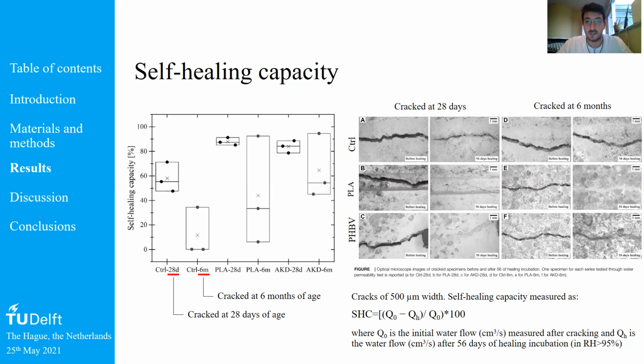So we can see how positive is the influence of our healing agents included in the matrix for cracks that are relatively big. That is also further confirmed by the pictures on the right, where you can see the first row related to the control series. Cracked at 28 days there is quite a bit of precipitates that cannot, however, fill up the crack completely, while for those cracked at 6 months the crack is more or less the same, so there is not enough precipitation to seal the crack for the control series. For both PLA and AKD, we see that the cracks get completely self-filled.